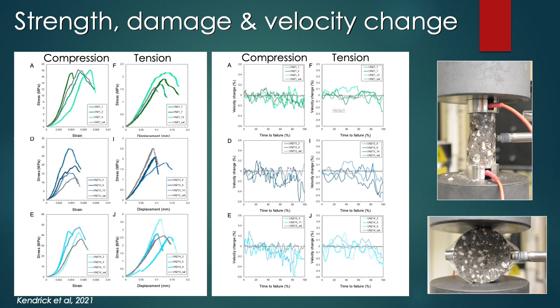In our tests, we found that this onset occurred at between 60 to 80% of the time or strain to failure. Such approaches have been used at large scale during volcanic eruptions to quantify damage caused during magma propagation, including during the spine extrusion at Mount Unzen in a study by Lamb et al. which we published in 2015. We see comparable reductions in velocity of up to around 0.4%, as are seen at larger scale, and this tells us that the material is dilating due to fracture damage before the final failure event.